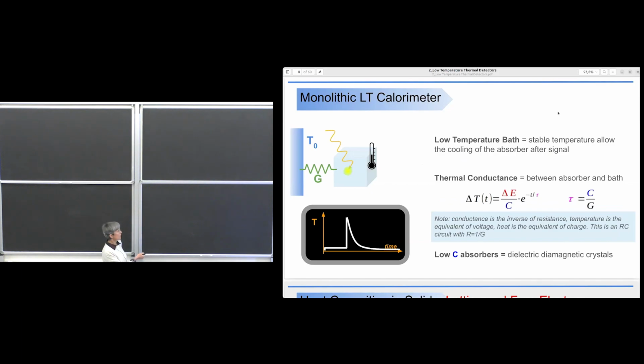Okay, so this is our new design of the detector. I have a thermal bath, and this will be my refrigerator, my cryostat, with a temperature that will never change, in principle. And then I have a thermal conductance that I call G. And in that case, my rising temperature will be transformed as you see here. After the increase in temperature, I will have a cooling of my absorber back to the starting temperature. And this is the evolution of the signal in time.